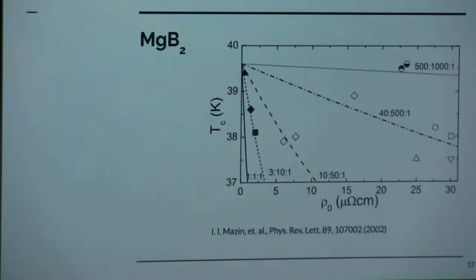A different example is magnesium diboride. Here again, we have Tc and resistivity, and each point in this scatter plot is a different sample with different qualities. And notice that Tc does not vary appreciably. If you apply a simple theory of two-band superconductivity, this would predict that superconductivity should be suppressed in two-band superconductors. But this does not happen in magnesium diboride. And I will shortly explain that this is related to the additional degree of freedom in this system.